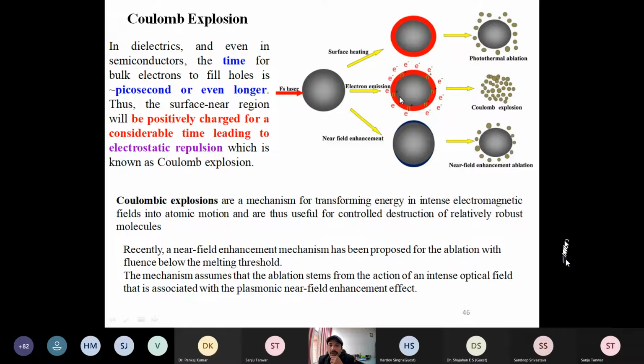Those holes are not going to escape, because the transfer of additional electrons from one point to another takes around a picosecond, while within the femtosecond time the density of both the electrons and the holes increases. So it becomes an electrostatically very unstable situation, and that's why an explosion takes place. So when the femtosecond laser hits the surface, a Coulomb explosion takes place.